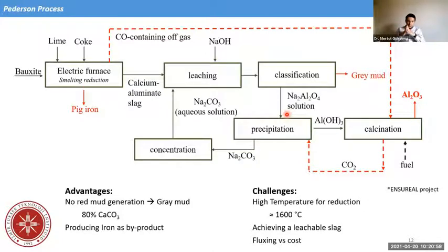The Pederson process is doing pyrometallurgy first. It first reduces bauxite as it is with carbothermal reduction, and produces iron and some other base metals which are reduced with iron, like silicon, like manganese, cobalt. And then we have an iron alloy. Then we have a slag. This is calcium aluminate slag. And it goes to a hydrometallurgical process, leaching, like the Bayer process actually. And then the product is aluminum oxide to be processed in molten salt electrolysis again.